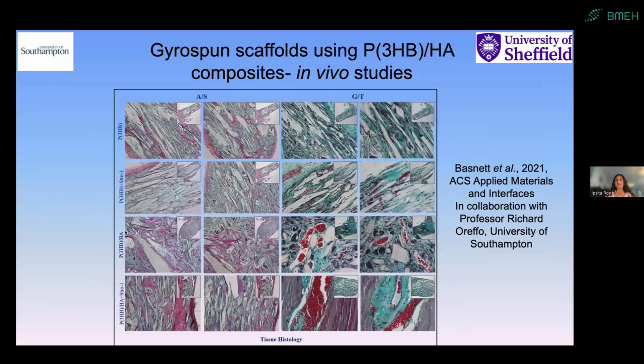We then went in vivo in rat, and what was seen is that the top row here is P3HB only, gyrospun fibers. This is P3HB with STRO-1 cells, which are bone cells, and you can see that the cells are growing, attaching really well, with STRO-1 cells already seeded onto the P3HB. Then the next one is P3HB and hydroxyapatite. You can see here that the vascularization is a bit more. And then finally, we did P3HB-HA with the STRO-1 cells. And you can observe here that we got beautiful vascularization and collagen formation, indicating that these gyrospun scaffolds are excellent for bone regeneration.